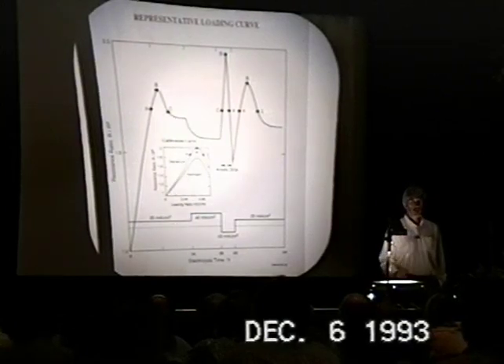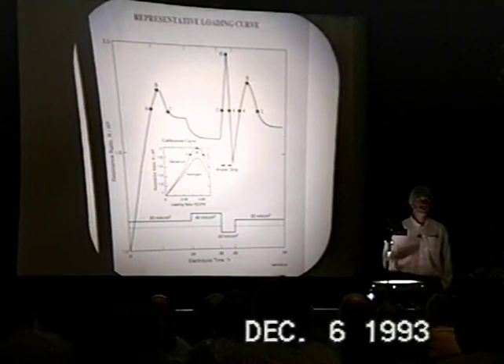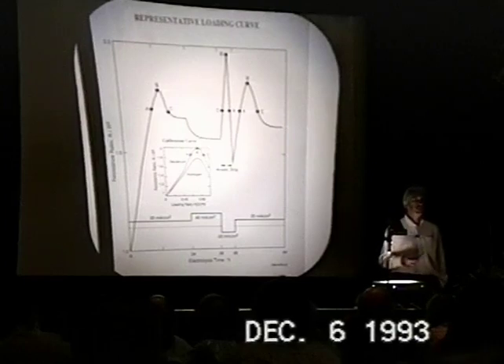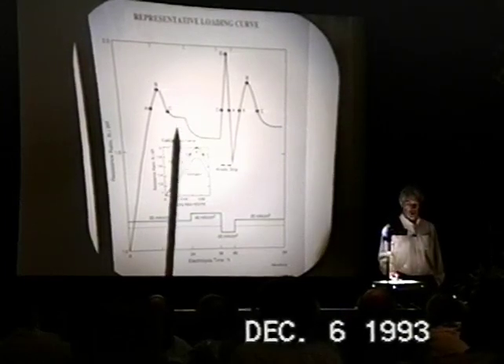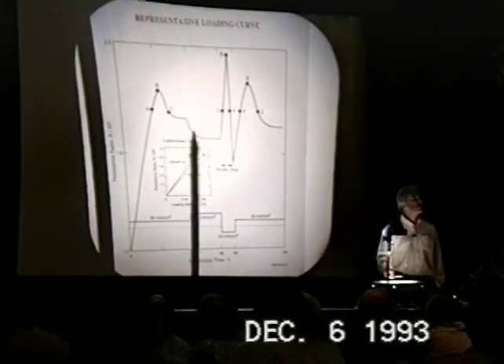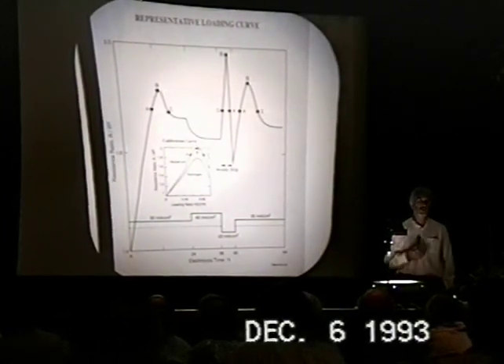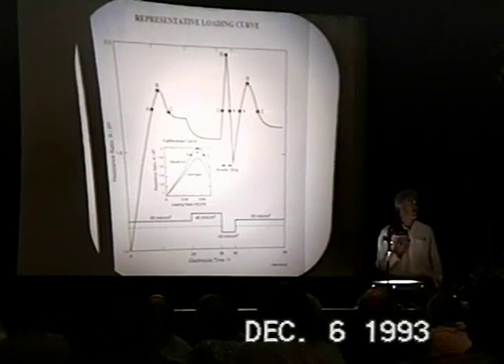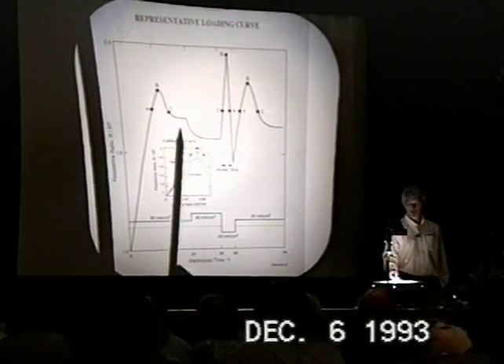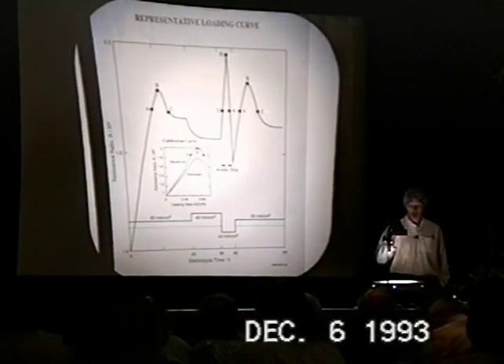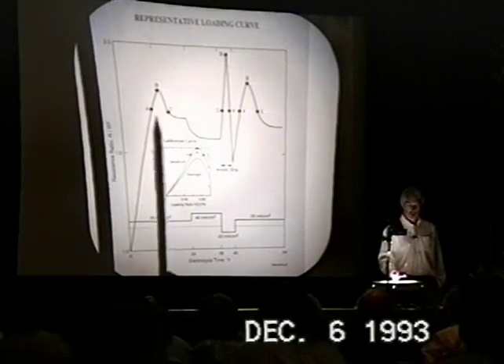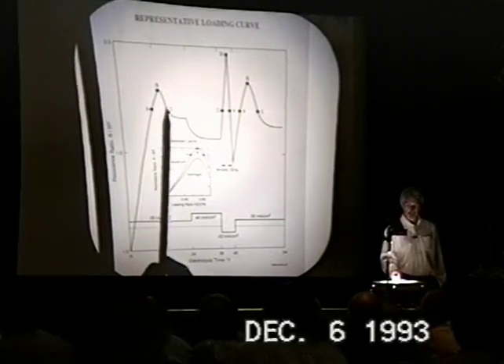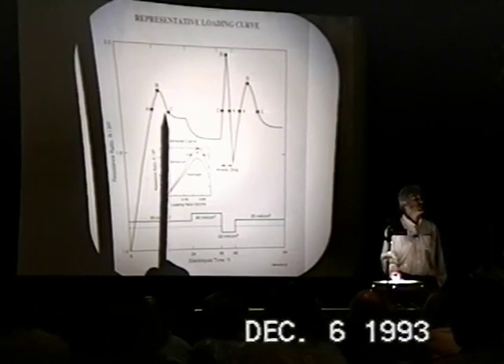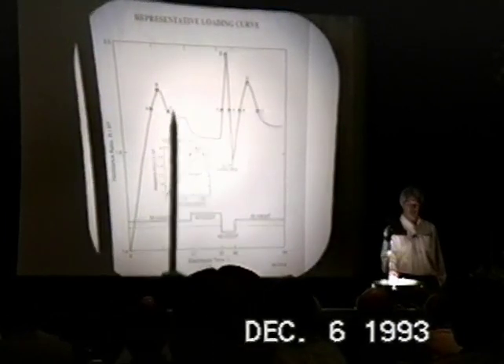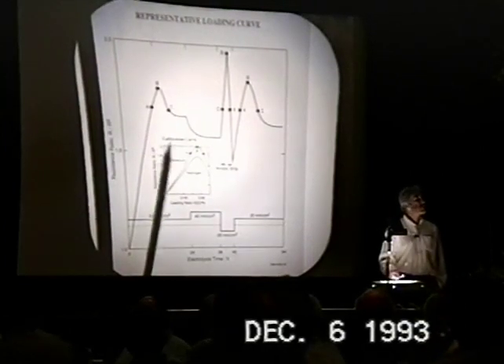A very good test of the ability of a particular surface preparation to facilitate loading is the response of the resistance ratio to increasing current density. If, on applying increased current density, the resistance goes down, you can be fairly well convinced that, one, the cathode is able to absorb more deuterium, and obviously that we're on the right-hand side of the maximum and not on the left-hand side. There's been some discussion. This curve obviously is double-valued. Value A and value C are the same resistance ratio. The question is, how do you know that you're at C and not at A? Well, the increased current test is one.